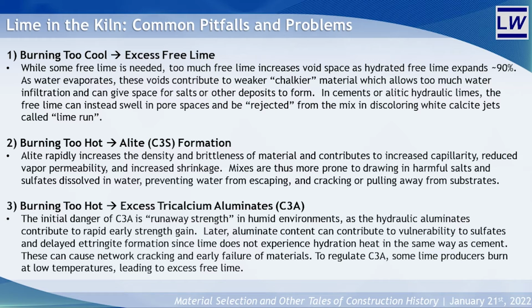Not only do these voids weaken the material flexurally and compressively, but they also contribute to drawing in excess moisture, which brings with it dissolved salts and sulfates, two of the most deleterious substances to masonry. In mixes that are combined with cements or have a great deal of alite, the free lime has no place to go and is jettisoned from the curing material, forming aesthetically unpleasing calcite streaks often known as lime run. In materials rich in hydraulic material, failure to control the temperature of the kiln by burning too hot or for too long results in mixes rich in alite.